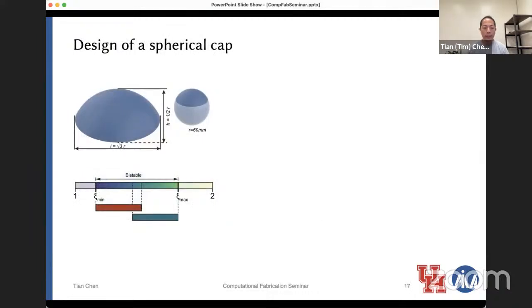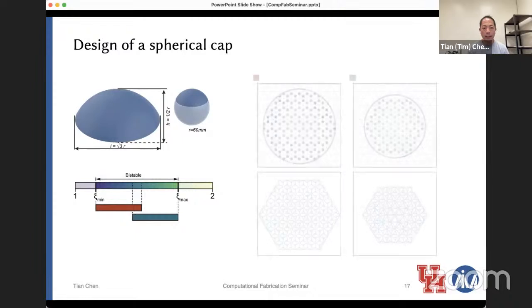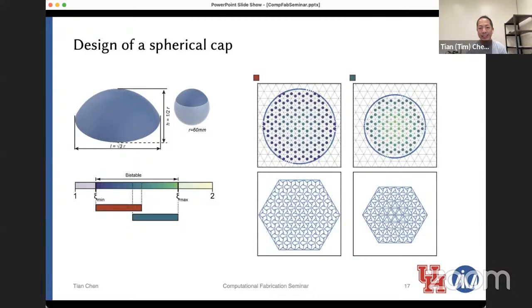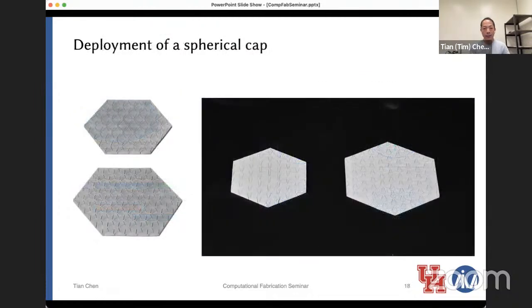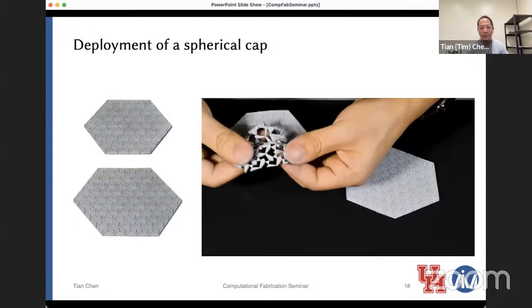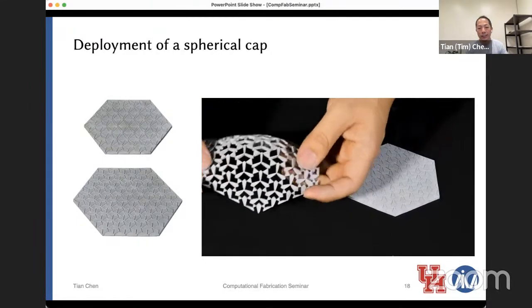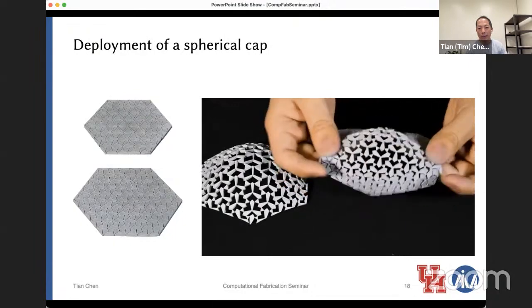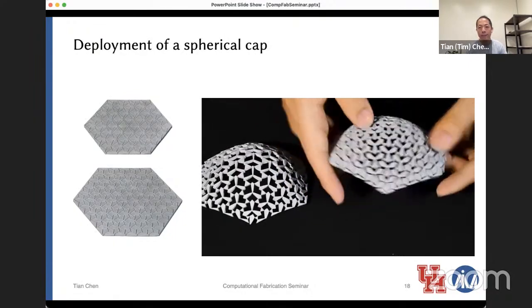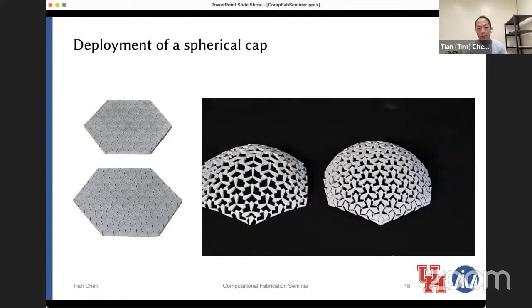With a simple example of a spherical cap, we intuitively know that we need the middle of the spherical cap to expand more than the edges. We can vary whether the middle expands a medium amount and the edge expands none at all, which means we can clamp the edge if we want to, or the middle expands a lot and the edge expands around a medium amount. As for deployment, this material is not smart or functional in any way, so we need to use our fingers to deploy it. Fortunately, the snapping of one unit cell triggers the snapping of the neighboring unit cell, and the deployment remains quite easy.